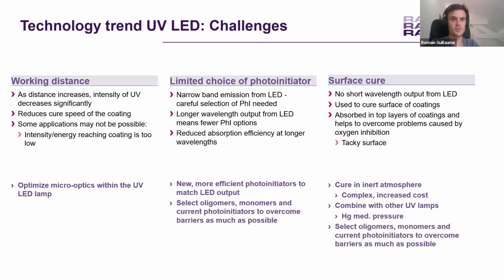So it could be seen as the reduction of the speed of the coating line and so on. Because of that, some applications may not be possible. So we work on optimizing the UV LED lamp with micro optics, with different optical designs, in order to fight against this issue and to allow us to have more energy. The efficiency and the power that one LED is able to emit is still increasing, and that will allow the system to reach the same amount of energy as a classic mercury lamp.